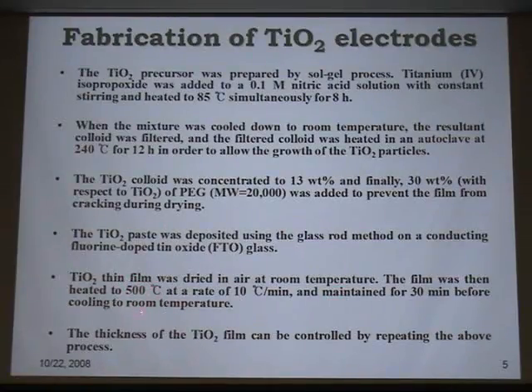You need to heat up to 450 degrees C to 500 degrees C, especially at a certain rate. If the rate is too high, you will destroy the nanostructure. And if it's too low, it will take too long to get the right structure. So the temperature rising step is also a key to this process.